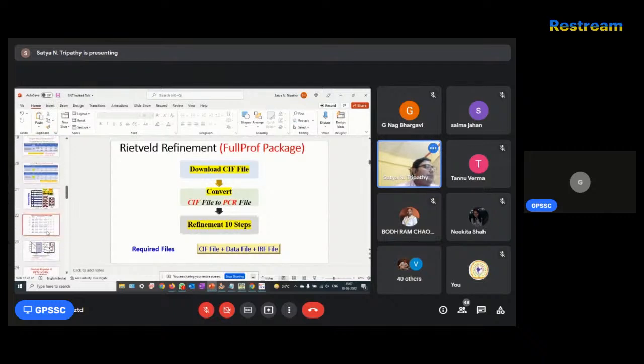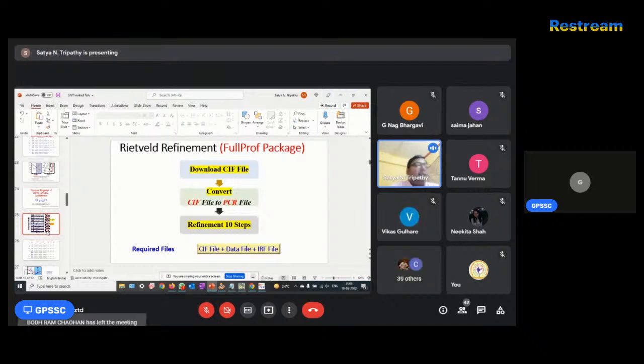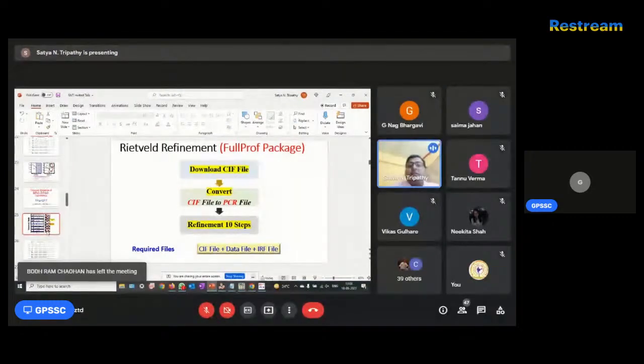So I'd like to conclude now that what we have done today, we have understood Rietveld refinement using the FullProf package. We have different kinds of samples like bismuth ferrite, a magnet-related compound, then gadolinium manganite, dysprosium manganite solid solution with bismuth ferrite, and a ferroelectric system like the NBT-BT system. We have done the Rietveld refinement. We saw how we analyze the data, and next we saw the microstructural plot and all this.